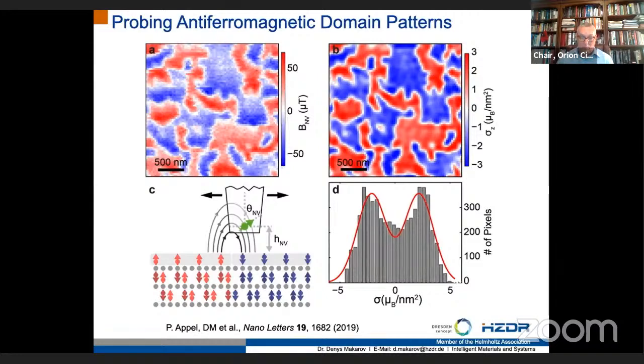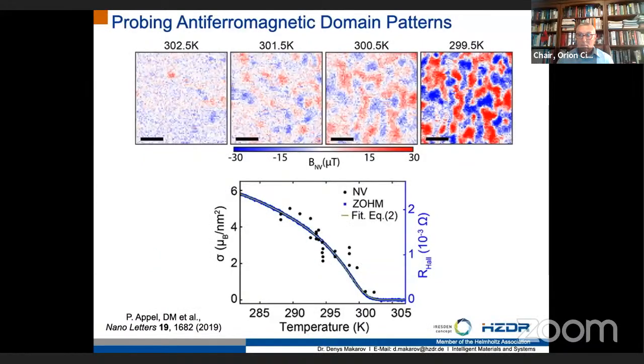The strong advantage of NV microscopy is that it provides you a possibility to access not only the quantitative stray field distribution over the sample, but also the magnetization of the sample. Now you can monitor the change of the contrast as a function of temperature. And in this case, you can get even access to the transition temperature from antiferromagnetic to paramagnetic state by determining when the contrast from the antiferromagnetic domain pattern disappears. In our case, this temperature is about 302 Kelvin, which is a couple of Kelvin smaller than the high quality single crystalline materials of chromium oxide.